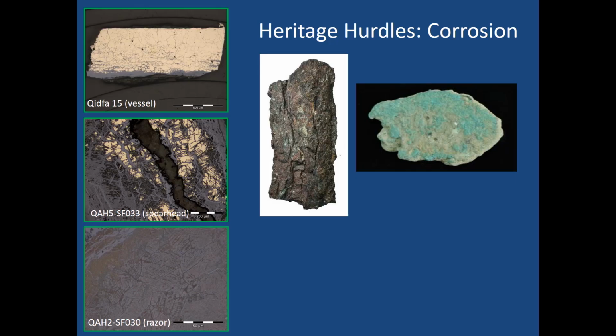Sometimes, as you can see in the example on the upper left-hand side, which is in a polished section, the corrosion can be relatively superficial, and behind that, there'll be very well-preserved metal. In other cases, as in the example in the middle left, there'll be a little bit of metal left behind. In other cases, as in the example at the bottom, there'll be virtually no metal left in the sample at all. And certainly, the preservation of iron remains at the site is often even worse than our bronze remains. Sometimes we have a little iron preserved, but more often our samples look like this.